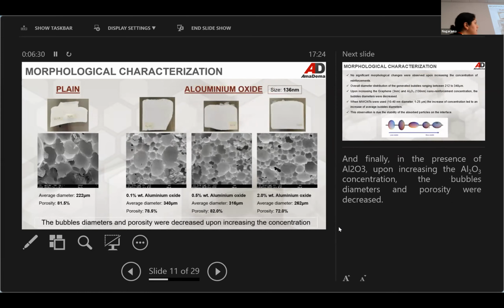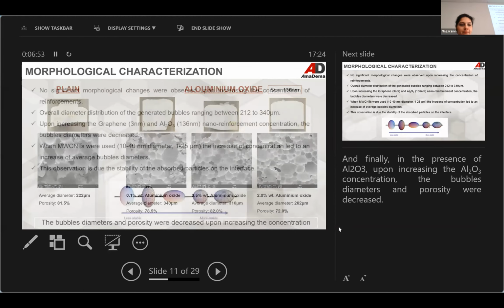And finally, the last system we've used were the aluminum oxide nanoparticles. As you can see, the size is also different here. And here we have observed the largest average diameter in the systems we've checked. And again, the bubble diameter and porosity are decreasing when we increase the concentration of aluminum oxide in the epoxy foams.